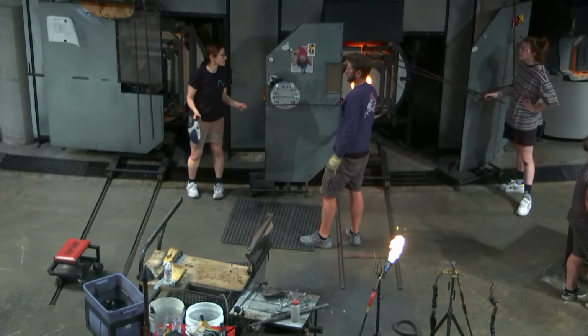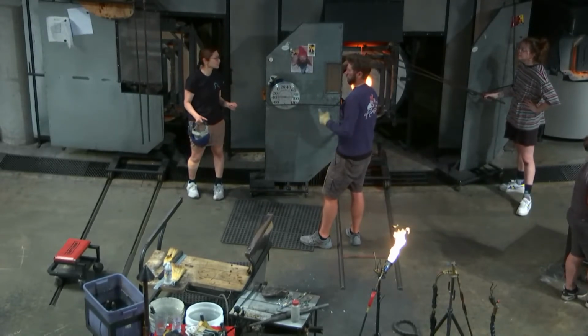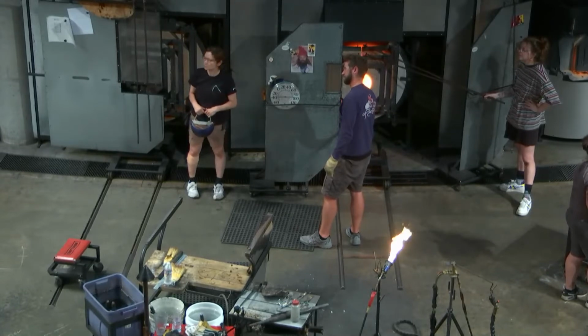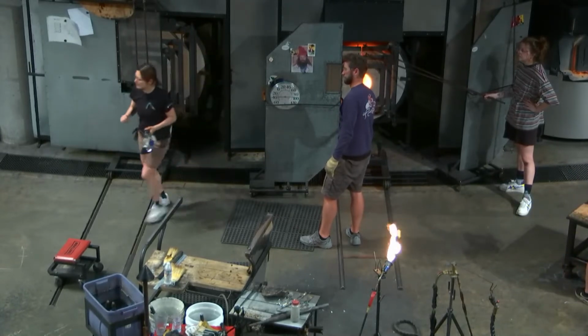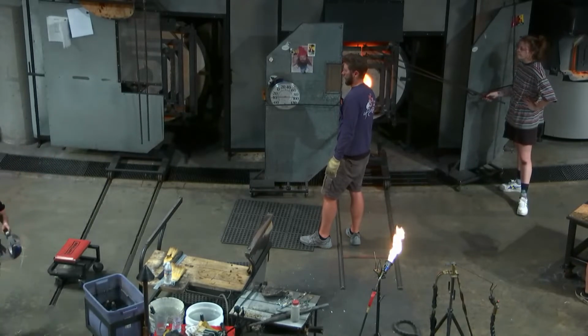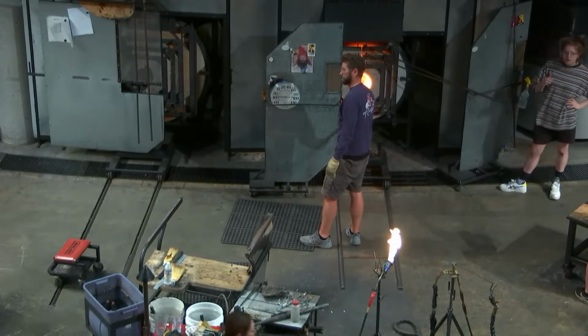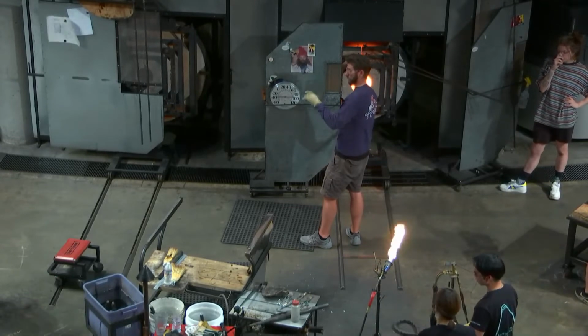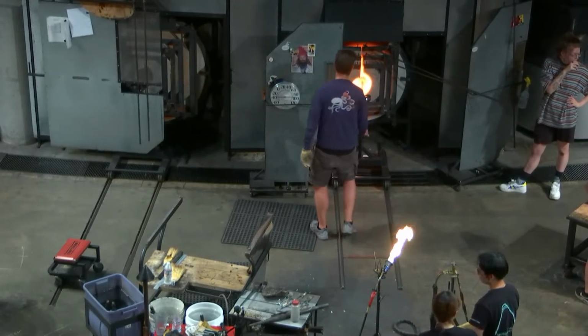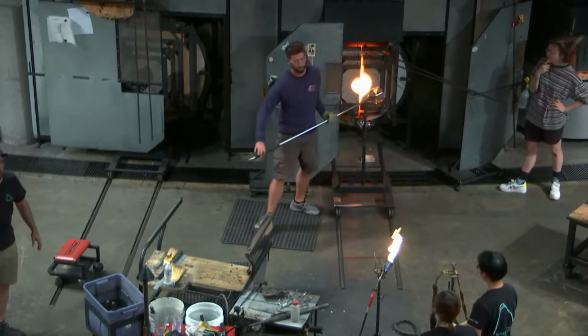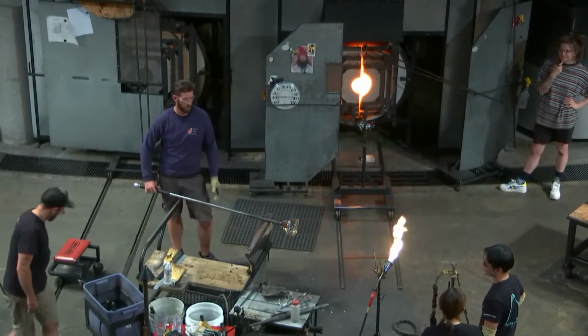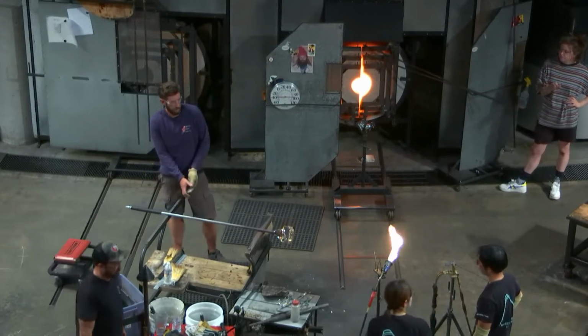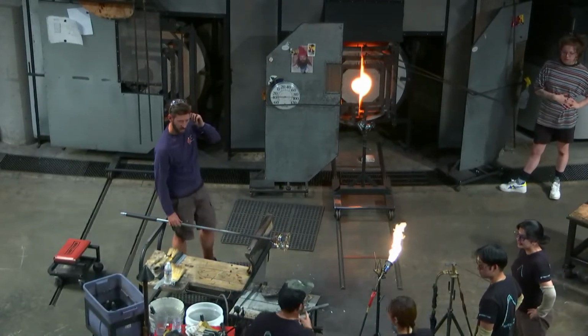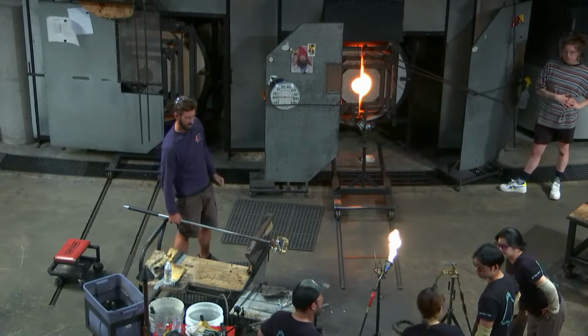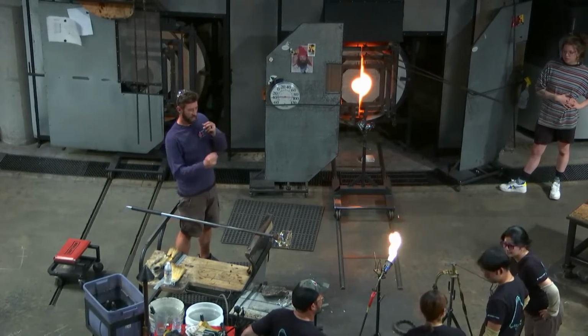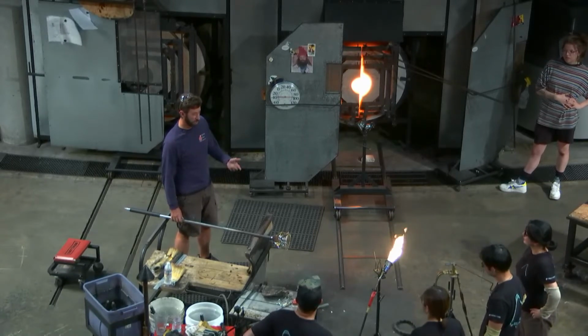So we don't want to lose the glass that has been created. So instead of just throwing it away, we're going to put it into an annealing oven. Because we already ramped it up, we want to cool it down at an even temperature. So organically, that woven glass has already been baked up to the proper temperature to allow it to fuse together. So now everything that was woven had been fused to a certain degrees. And unfortunately, it didn't quite wrap around that coil. So we took it to the oven so it can bake down properly to prevent thermal shock.